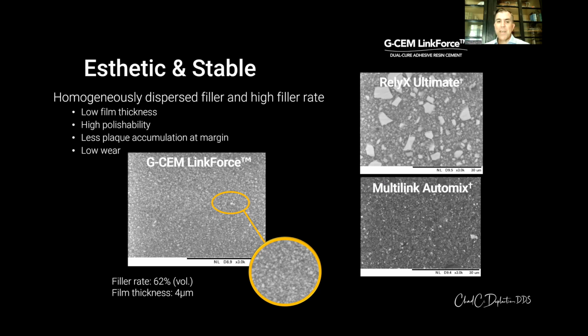And so we have a 4-micron film thickness, which is very good. It's not going to distort the seating of your restoration, and a filler rate of 62%, which compared to some of the other competitors on the market is very impressive.